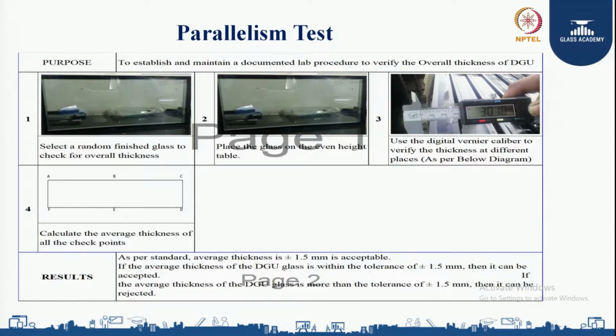As the DGU is a combination of two glasses with an aluminum spacer, we need to ensure the overall thickness of the DGU through a parallelism test. First we take a DGU finished product and place it vertically. Then using a digital vernier caliper, we measure the thickness at the center of the four edges, as shown in the figure at points A, B, C, D, E, F, and take the average thickness.